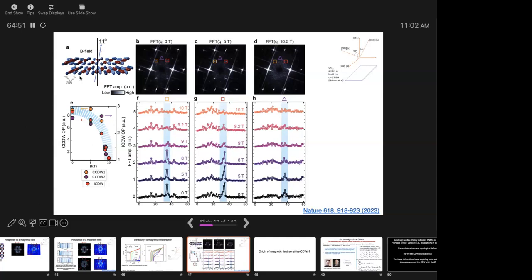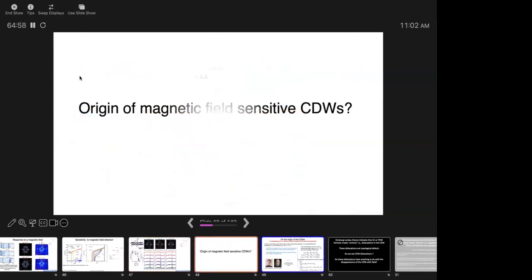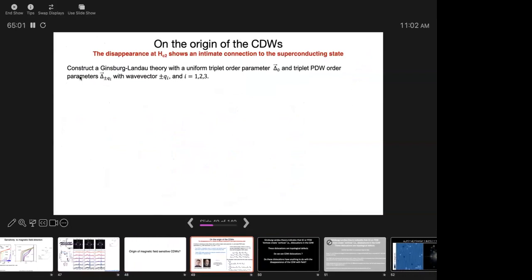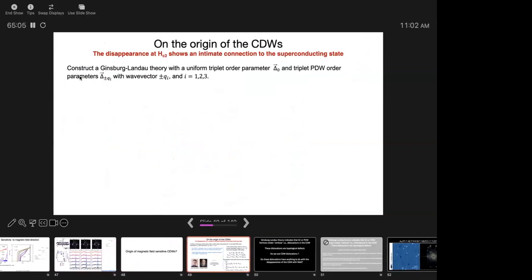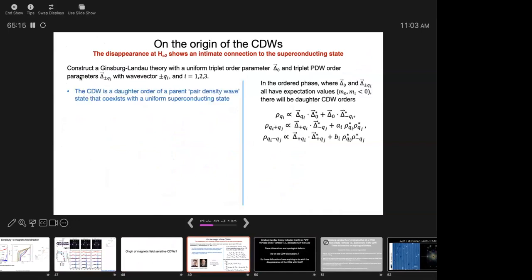So the question is, why is this happening? Why would a charge density wave get suppressed at HC2 or close to HC2? One possibility, proposed by my colleagues Eduardo Fradkin and his student Julian Meyman, is that there is a pair density wave in the system. Take a Ginzburg-Landau theory of a uniform triplet order and a triplet pair density wave order. It doesn't have to be triplet, by the way. The only reason we thought about a triplet PDW is because it's sensitive to magnetic field direction. We have to explain the sensitivity to direction somehow, and one way is to assume a triplet PDW. Then you can have a charge density wave order as a daughter order.